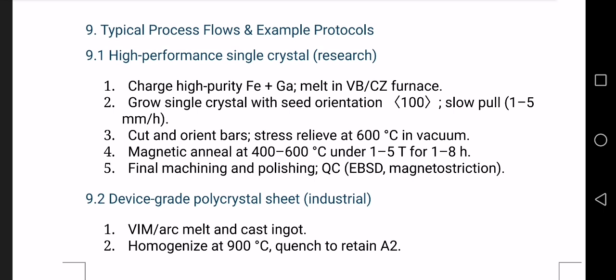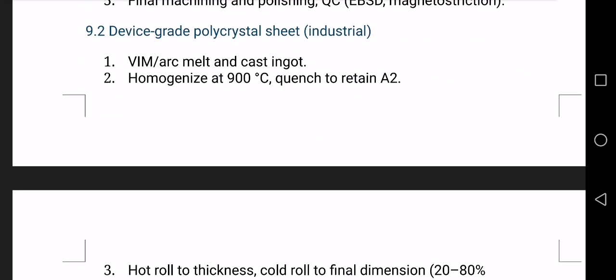Now let's see the steps. Melt high purity Fe and Ga. Grow single crystal using VB or CZ. Orient along 100 directions. Stress relieve at 600 degrees Celsius. Magnetic anneal at 400 to 600 degrees C under 1 to 5 Tesla. Final polishing and QC.